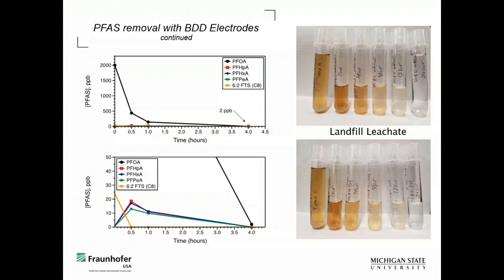This was a good result in that we were able to remediate the short chains as well, but the detection limits for this method were about 8 ppt. So that's where we thought in our flow-through system, maybe we do have efficient enough mass transport because we would have seen these if they were still there. So that was one sort of promising thing, and we've done a lot of other experiments.